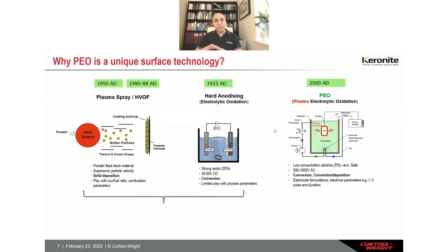The other benefit of the PEO is you often use an environmentally safe electrolyte, at very low concentration, less than 5% solid content. It's typical of a dishwasher liquid that could be disposed of to the normal sewage systems. So this makes the technology unique, and also because it is an electrolytic process, you can coat extremely complex shapes, which are poor line of sight.